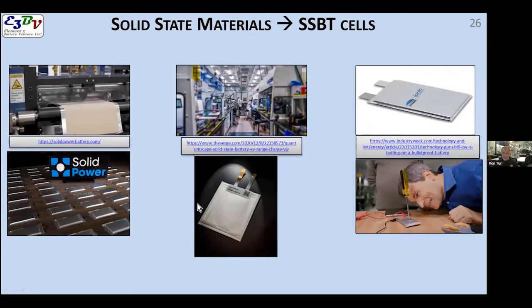It defeats dendrites. Lithium can grow and plate, but it forms needles if it's non-uniform. And those needle-like dendrites are like tiny pins that, even though they're soft and they can't really penetrate on their own, the growth of the dendrite eventually wins out and penetrates through softer materials. And if you have a material like this, which has probably 30 gigapascal Young's modulus, something like that, it can maybe resist forming a hole in the separator over the course of 10 years. At least that's the approach. These are better ionic conductors. You can make them thicker.